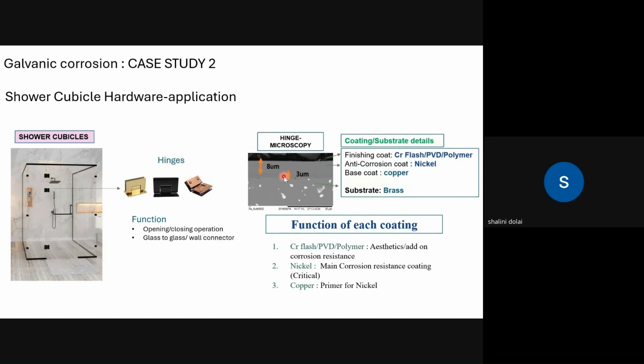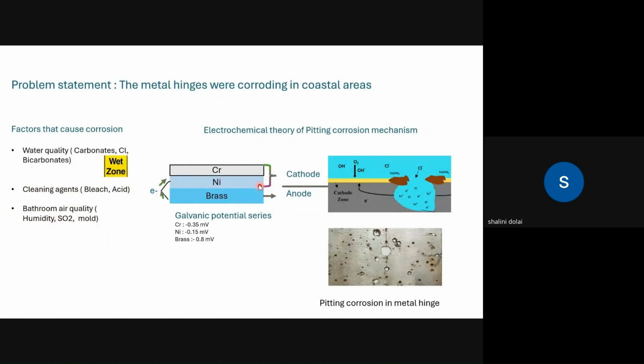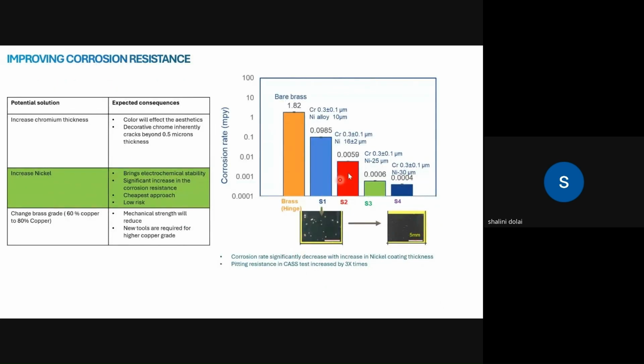So again, we studied the corrosion rate of each layer. We tried to understand which one will act as cathode, which one will act as anode. You can see this kind of corrosion was happening. In this case, it is reverse. Brass is an anode, and nickel and chromium act as a barrier. The electrons from brass were getting transferred to nickel, and these kind of pits were getting formed. So whenever there is bleach or air quality is bad, this kind of corrosion was happening. So again, we did the electrochemical test, and we identified three possibilities.